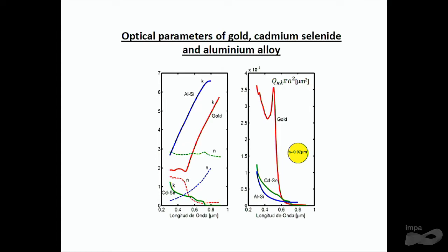These are the characteristics of gold. These are the characteristics of 3 different materials. This is the optical characteristics in bulk. You have the refractive indices. K is the imaginary part, N is the real part, of different materials. In red, you see the ones of gold that may not look particularly different than the rest. But if you transform this into efficiency, you have that gold has, at this wavelength that is around 500 nanometers, an efficiency that is around 20 to 30 times larger than a similar particle of the same size made of cadmium selenide or aluminum alloy.